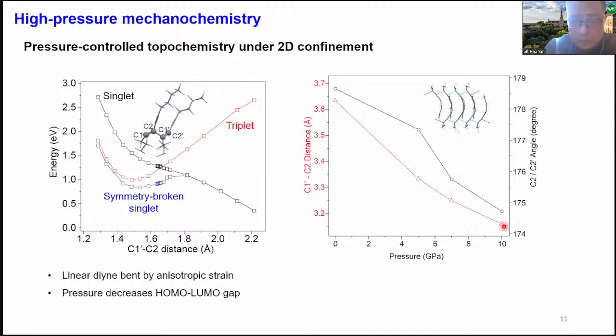Well, we modeled the transition state for the initial dimerization of the two adjacent diacetylenes. And what we found is that it takes two components. There's the spatial adjacency or vicinity of the C1 and C2 of these two adjacent diacetylene molecules that's needed to form the chemical bond. But also you have to realize that in forming this bond, the hybridization of the carbons goes from sp to sp2. In other words, the bond angle goes from 180 to 120. So there's also an element of the bending of the bond angle here.